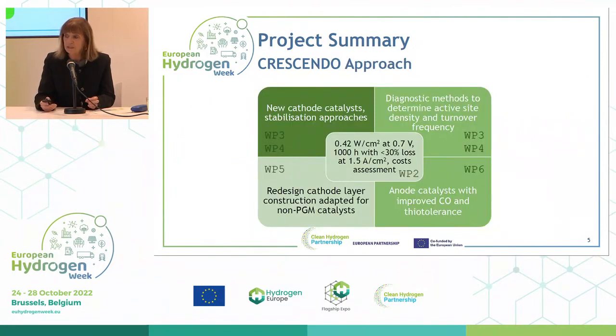So the approach here was clearly, on the one hand, because we were concentrating really on cathode catalyst development, because obviously there's more platinum at the cathode than at the anode, so it's more critical to replace that catalyst at the cathode than the anode. So we concentrated a lot on the development of new cathode catalysts to improve the activity of those catalysts, but